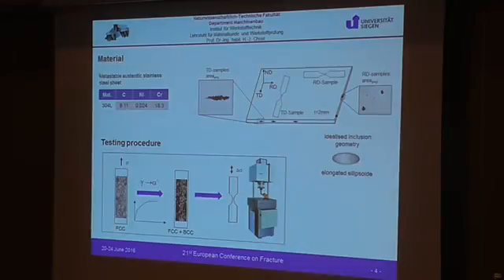The steel that I used is the AISI 304L, which is a metastable austenitic stainless steel. As said, it comes in the form of metal sheet with a thickness of 2 millimeters. The material contains a high number of oxidic inclusions, and these inclusions have a special geometry like an elongated ellipsoid. And these elongated ellipsoids are not distributed homogeneously, are not oriented homogeneously, but they have the longer axis parallel to the rolling direction of the metal sheets.